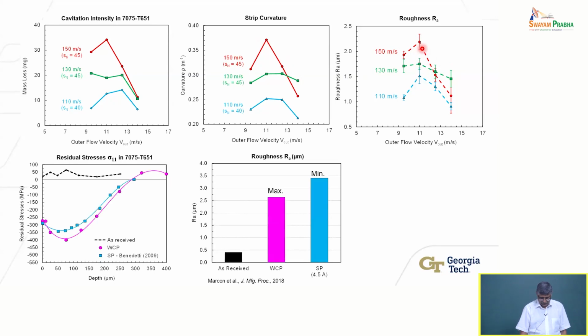So we did that, and you see here, this is roughness of the received sample, the aluminum sample. This is the maximum roughness we generated with our system, okay? Worst case at 150 meters per second and 11 meters per second outer jet velocity. This is data from literature for the same material using shot peening, mechanical shots.